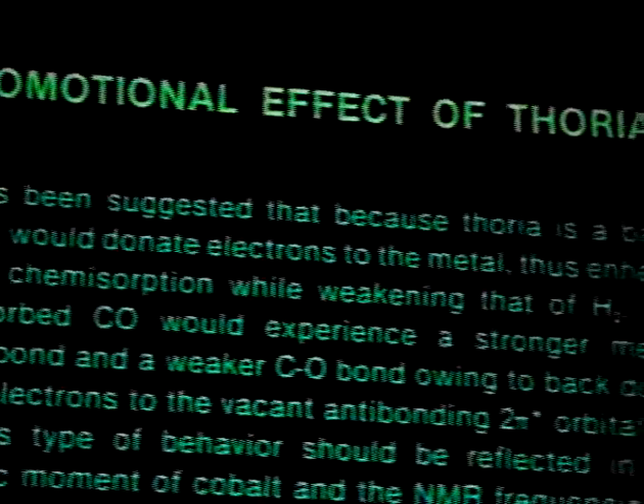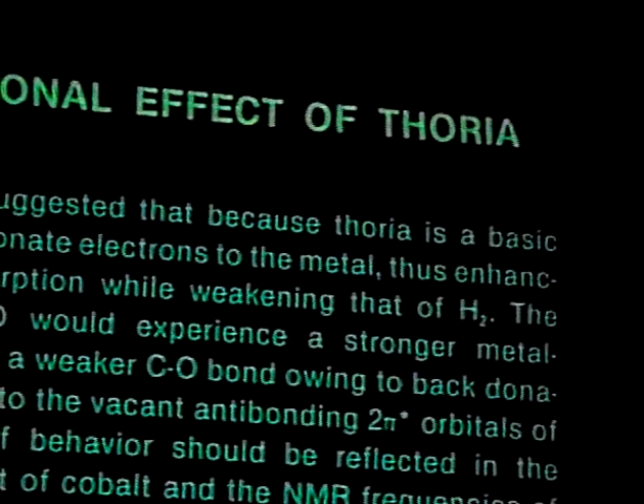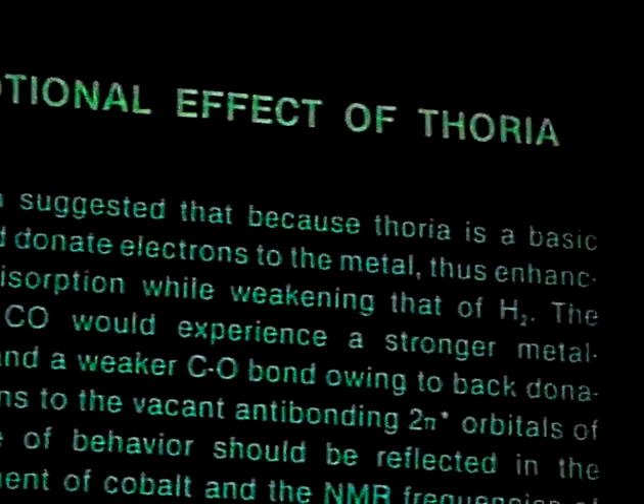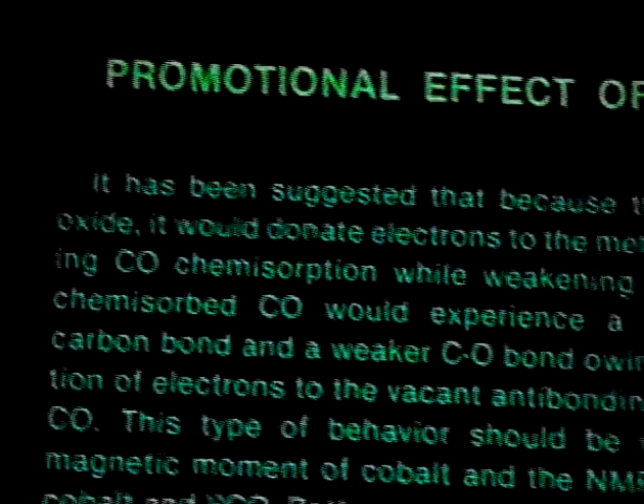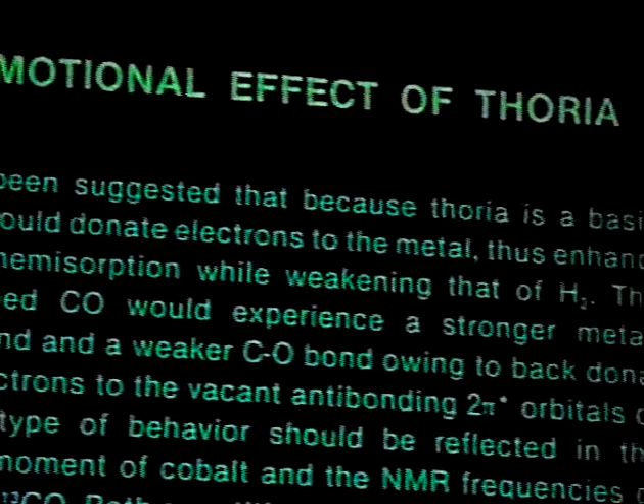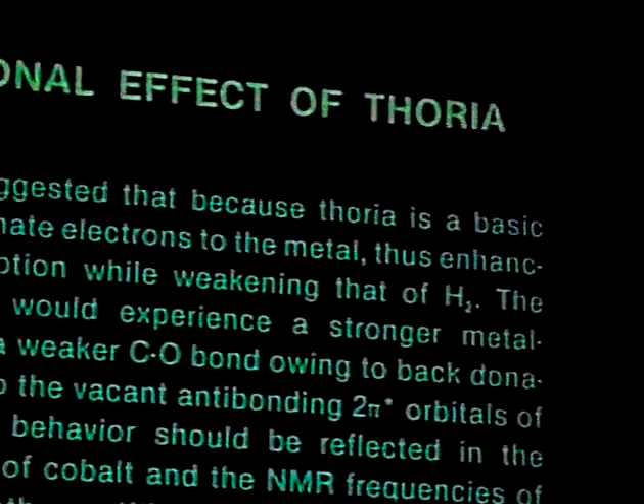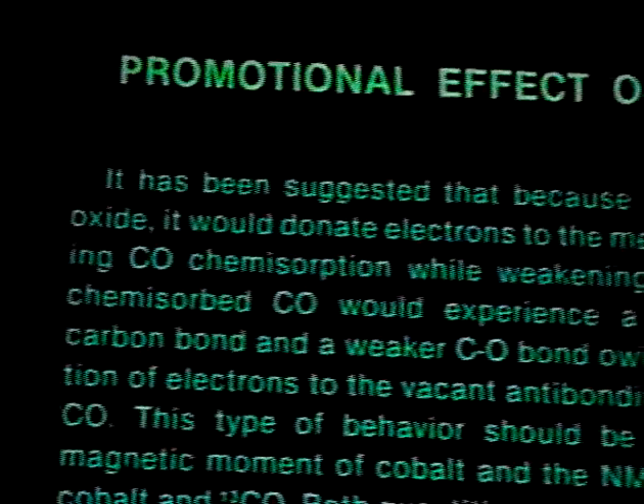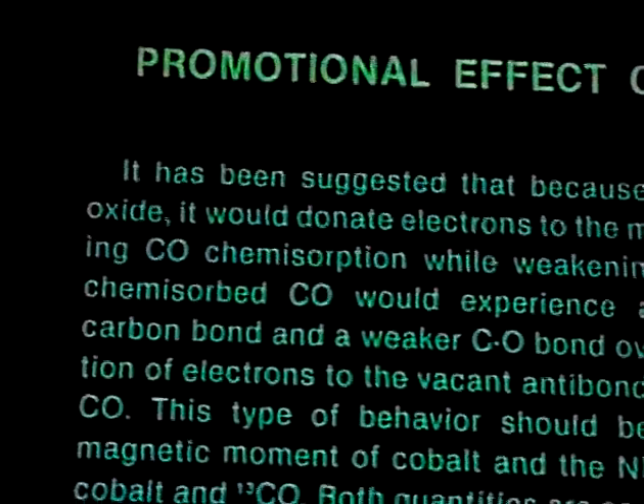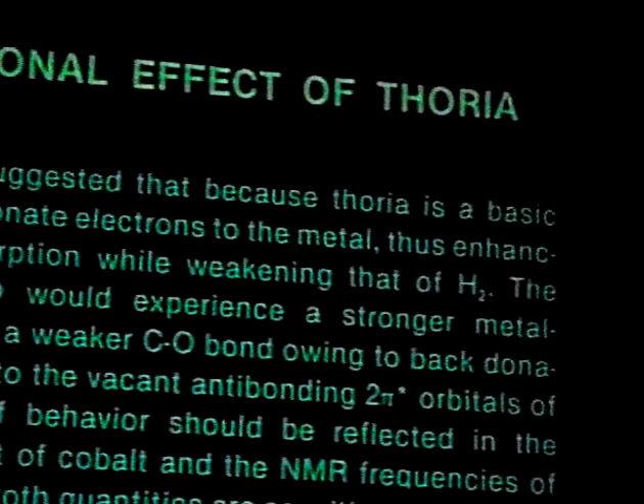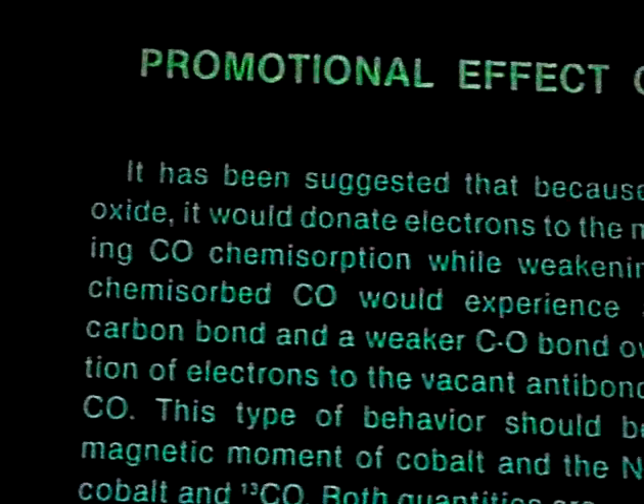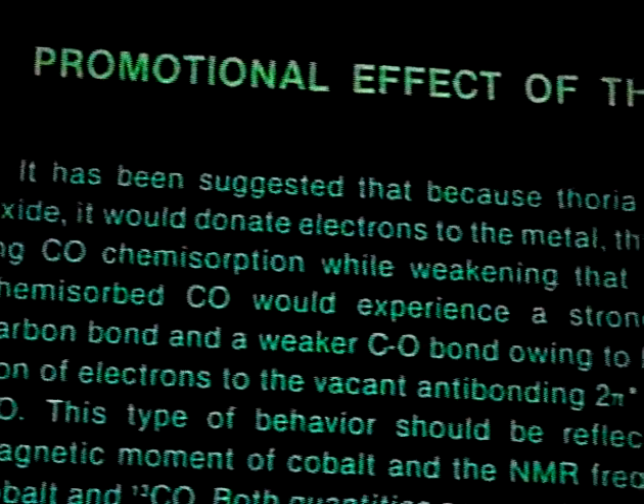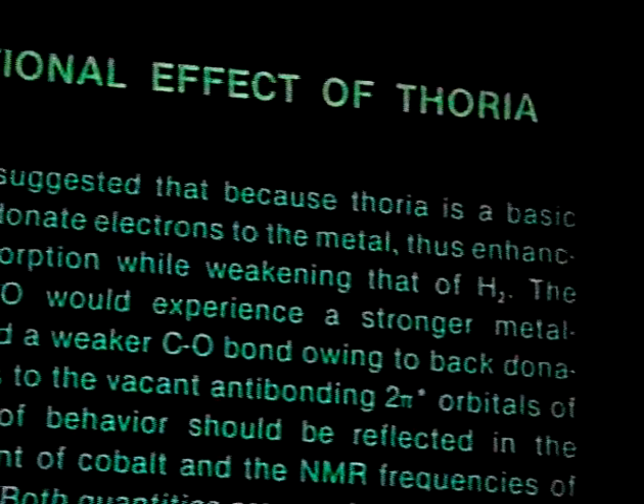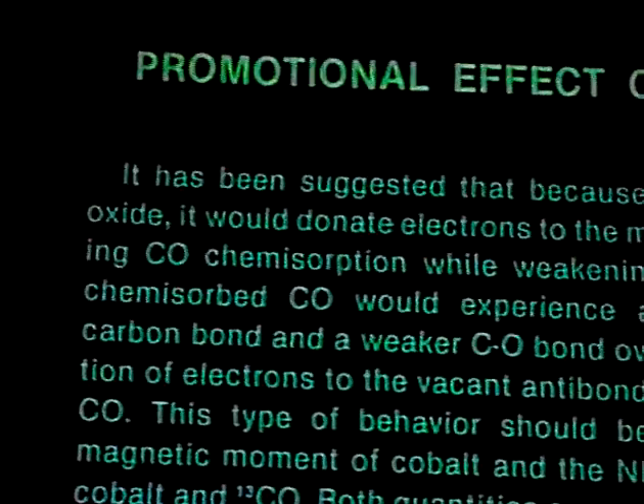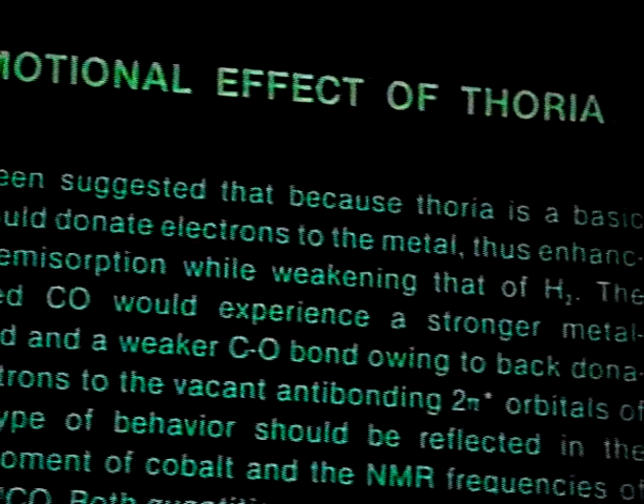Since thoria is a basic oxide, it would donate electrons to the metal, thus enhancing CO chemisorption while weakening that of hydrogen. Then the chemisorbed CO would experience a strong metal-carbon bond and a weaker CO bond because of back donation of electrons to the vacant anti-bonding 2pi star orbitals of CO.